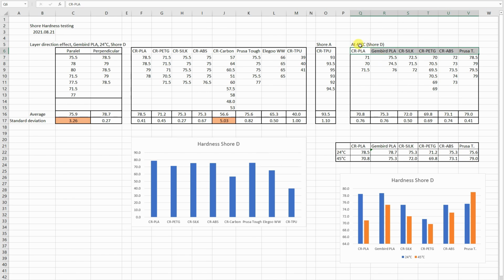Then in the next experiment I tested at higher temperatures, so I placed these materials into the filament dryer at approximately 45 degrees Celsius, and the standard deviation was okay in every case. And here they are. This table is at 24 degrees Celsius, which was the room temperature in that basement, and this was the temperature approximately in the filament dryer. I didn't measure it accurately. In every case, the filaments get smaller hardness, especially the PLA, except the resin. The Prusa Tough resin was actually harder after the filament dryer. I'm not sure if this is normal.